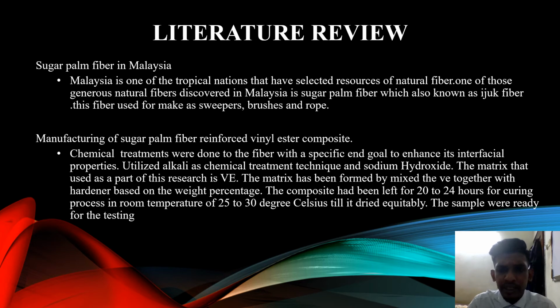The composite was left for 20 to 24 hours for the curing process at a room temperature of 25 to 30 degrees Celsius till it dried equally. The samples were then ready for testing.